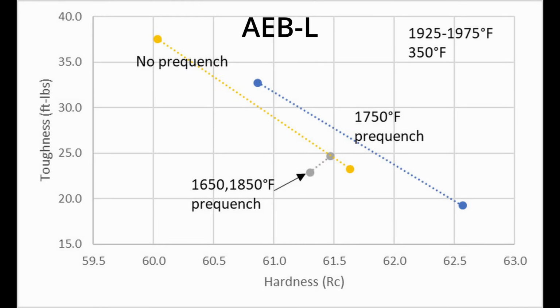And when I looked at the hardness-toughness balance, even though the toughness had gone down with the 1750 prequench, it did increase the hardness-toughness. So if we look at the same hardness with no prequench, we were either a little bit harder or a little bit tougher, depending on which direction that you look. But when we looked at 1650 or 1850 prequench, there was no improvement. And so it could just be statistical variability that the hardness-toughness balance ended up looking better with the 1750 prequench. Either that, or it is very sensitive to the temperature that we use for the austenitizing in the prequench.